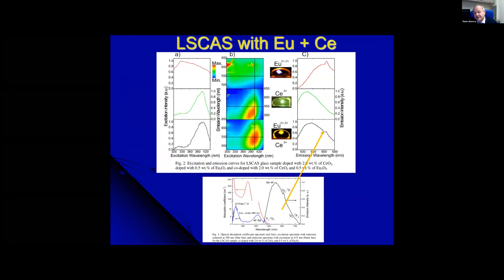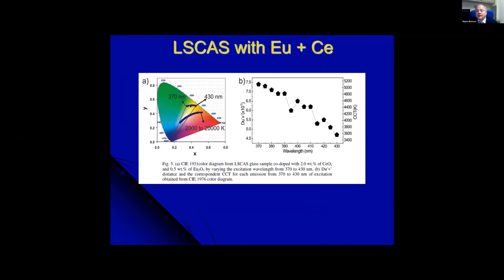This is very important, as I said in the beginning. It's very difficult to get a material with good emission in the yellow and especially in the red region of the spectrum. Of course, here we changed the LED excitation from 370 to 430 nanometer, and we get the Planckian temperature, the CCT, from the emission. So we can move from 3,000 Kelvin up to 5,200 Kelvin for the emission of the glass.